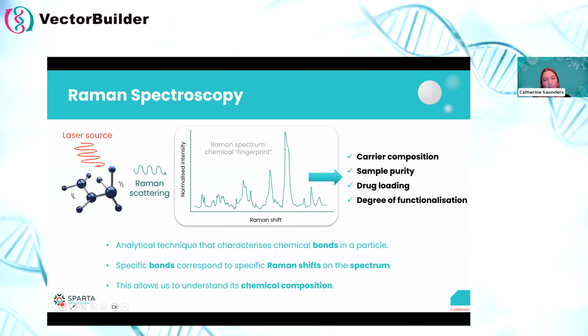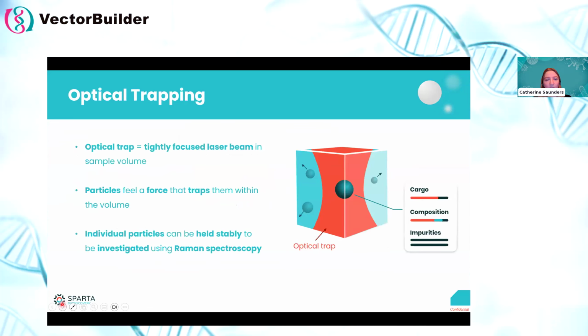So the information that you get out is in the form of a Raman spectrum, and you'll see there are different peaks here, and each one of these different peaks corresponds to a different chemical bond that is in the sample. So by analyzing these peaks and the relative intensity, we can gain really a lot of detail about the sample, kind of this snapshot, kind of simultaneously, including the carrier composition, the sample purity, drug loading, and functionalization. And we want to do this on the single particle level.